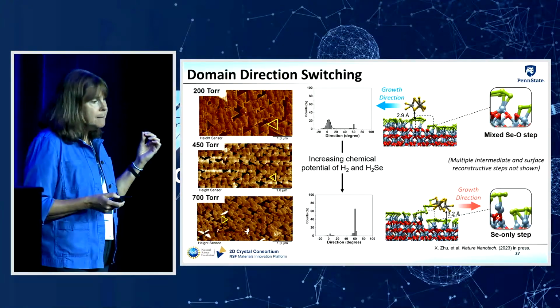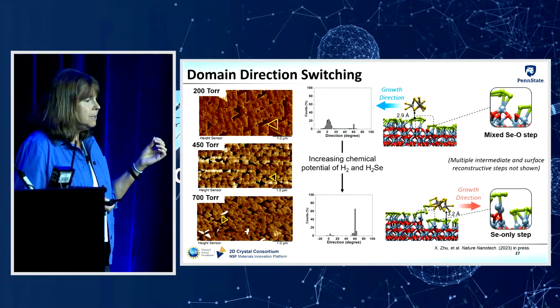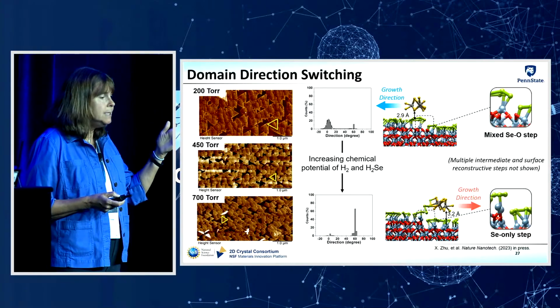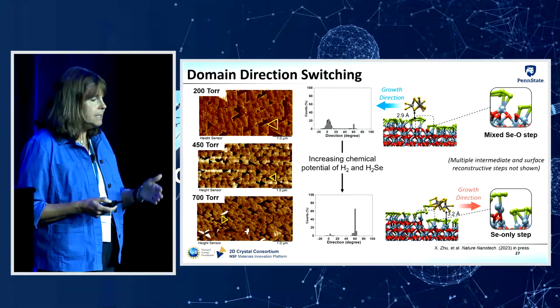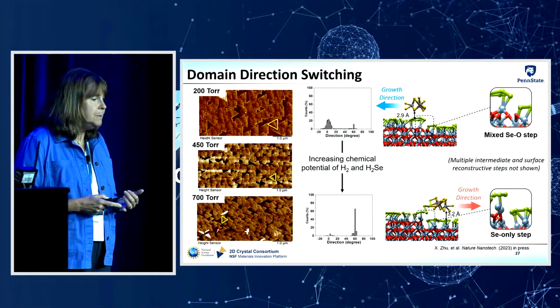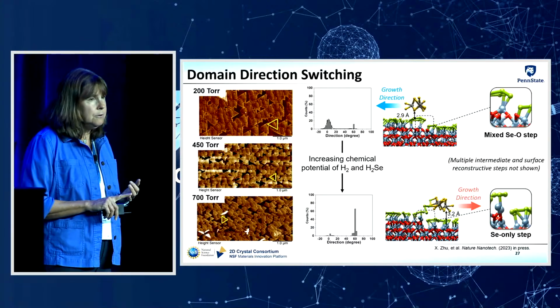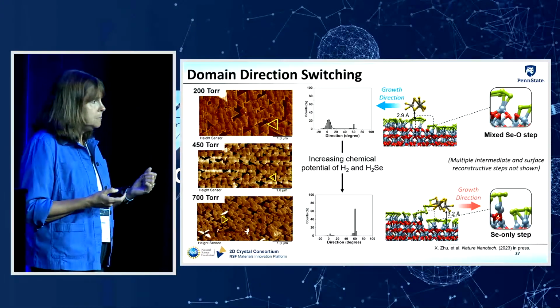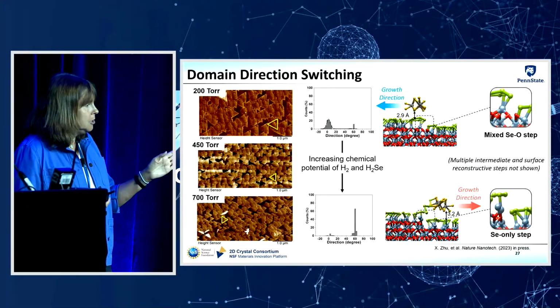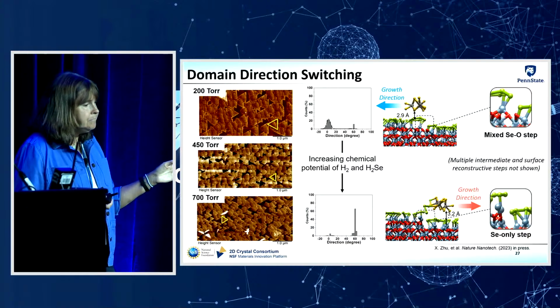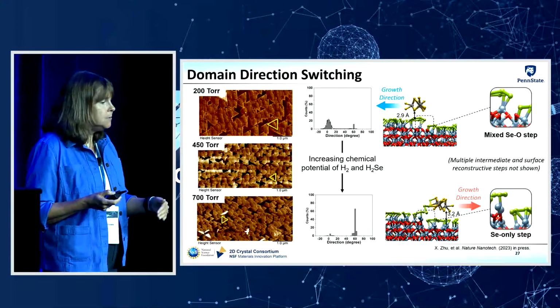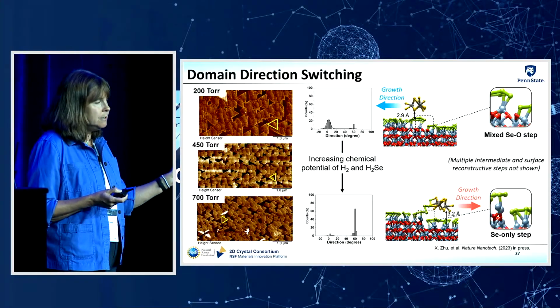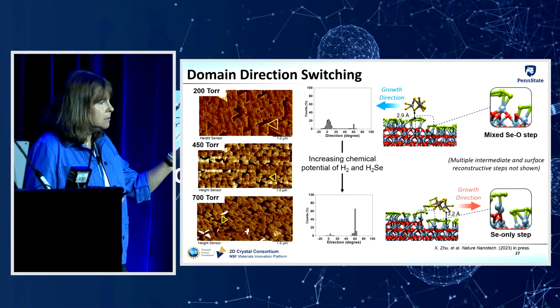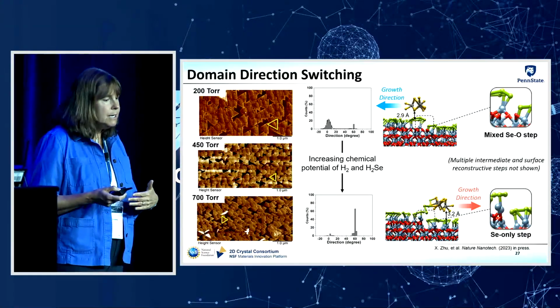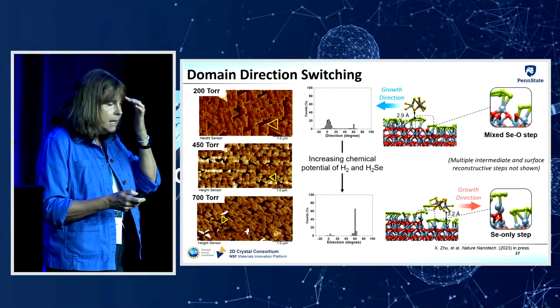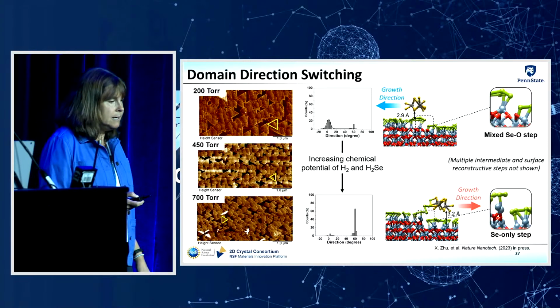So this is a series of AFM images for tungsten diselenide grown as a function of reactor pressure. So we're increasing the reactor pressure from 200 torr up to 700 torr. And that increases the chemical potential of hydrogen and hydrogen selenide in the growth ambient. So it's more likely at higher reactor pressures for us to have a fully tungsten terminated surface that's passivated with selenium. And what we find is that as we increase the reactor pressure, the orientation of the domain switches. So it changes from being 0 degree at low pressure to being 60 degree at high pressure, which is consistent with the model predictions just based on the step chemistry.